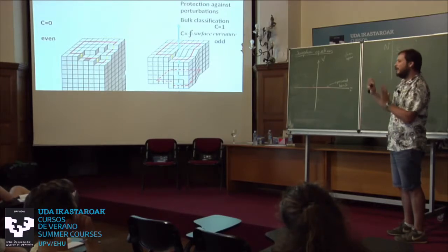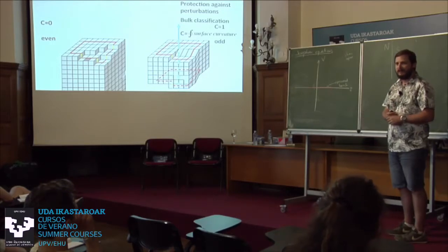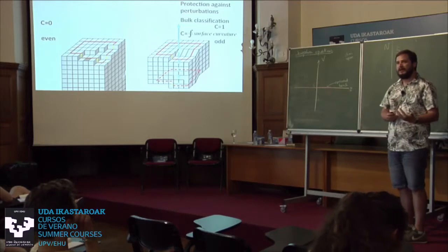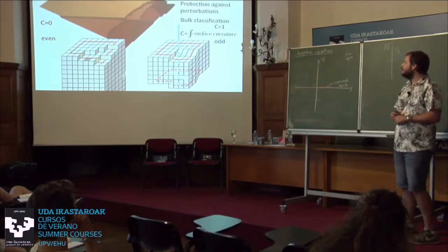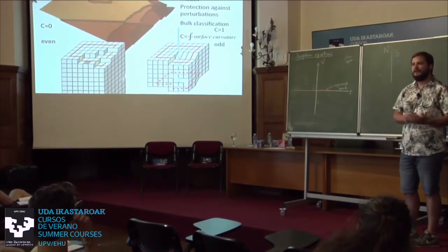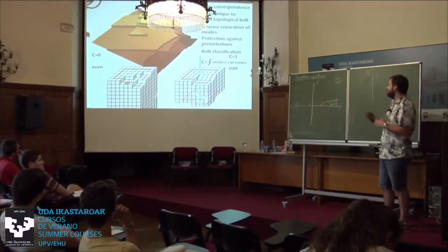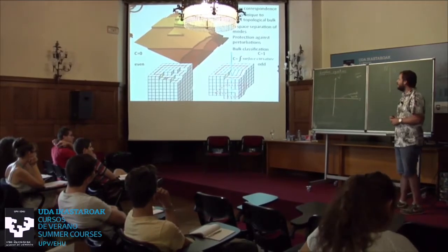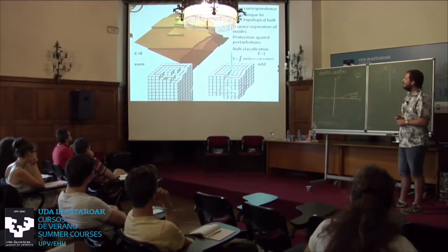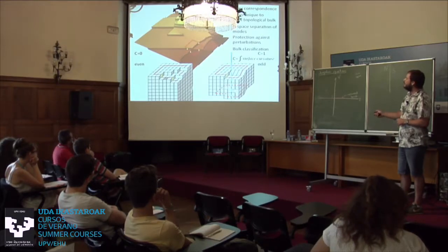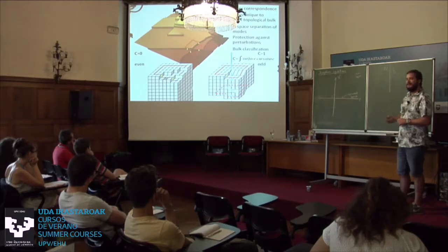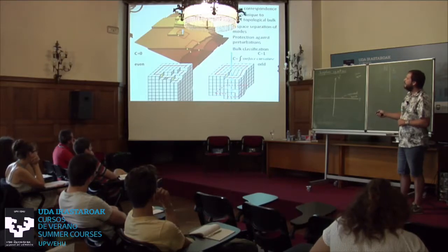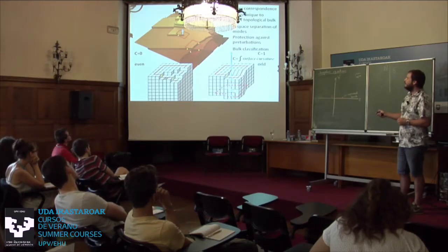This covers most of the phenomenology of topological materials, which is also exhibited by topological defects in real space. Here is an STM topography of the 111 surface of copper — a trivial material. Drawing closed contours, some regions cross step edges an even number of times, which is trivial. But drawing a contour in a different spot, I cross a single step edge, and I can identify within this contour the termination of a screw dislocation.